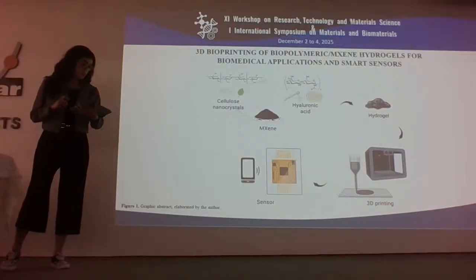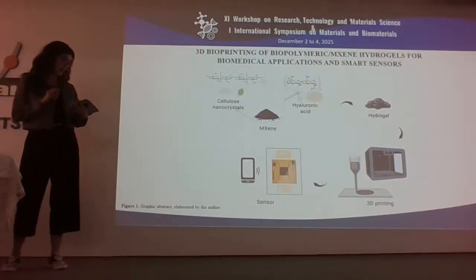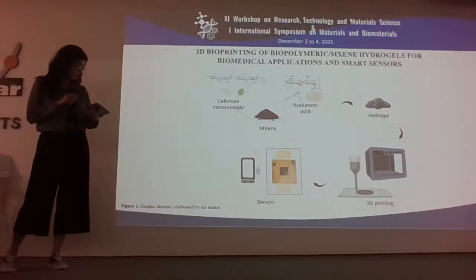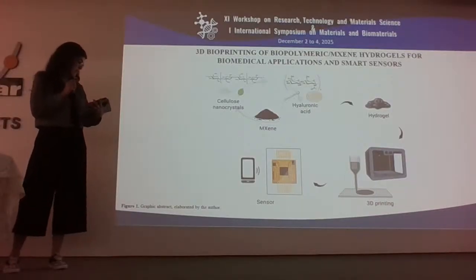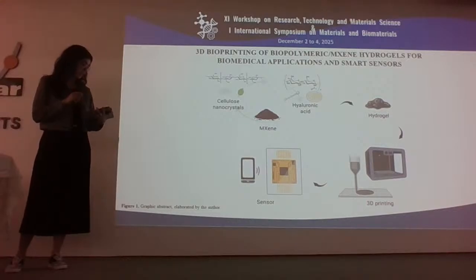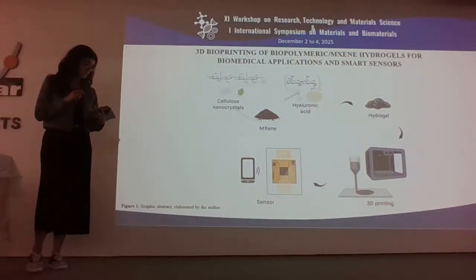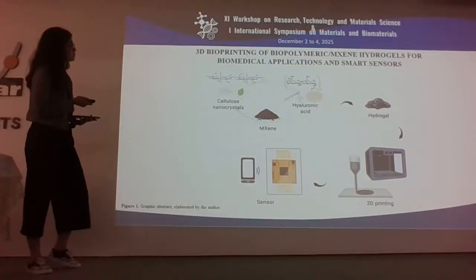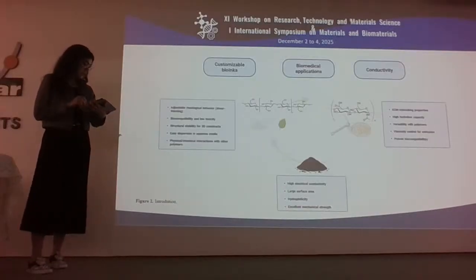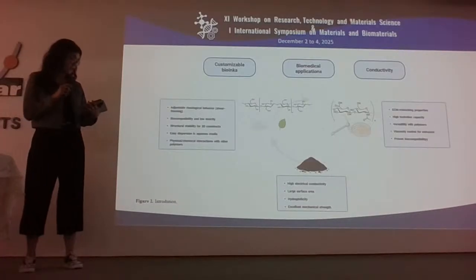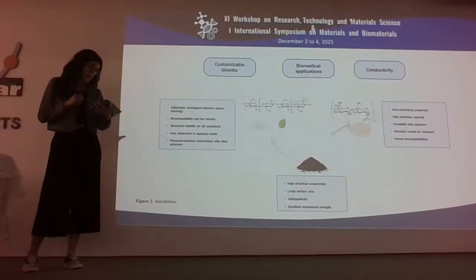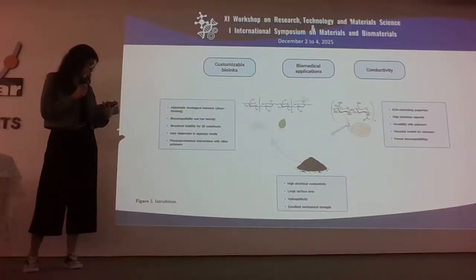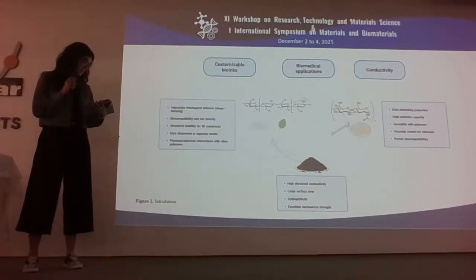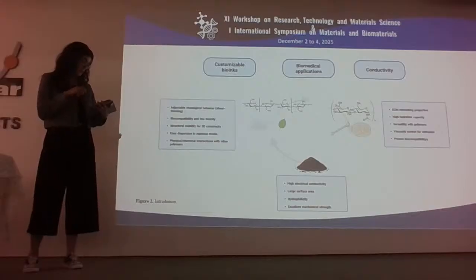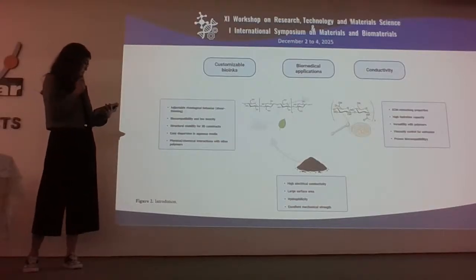For this purpose, we combined cellulose nanocrystals, hyaluronic acid, and MXene to create a biocompatible, conductive, and stimulus-responsive material for application in regenerative medicine and smart biomedical monitoring. We chose cellulose nanocrystals because they adjust the hydrogel rheology very well, provide the necessary shear thinning behavior, are biocompatible, and disperse easily in water, contributing to the creation of versatile bioinks.